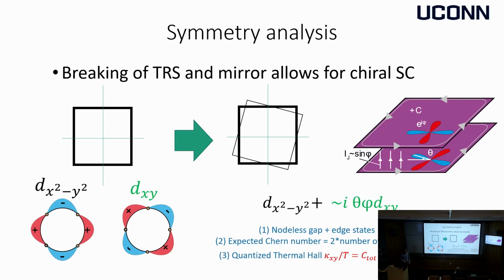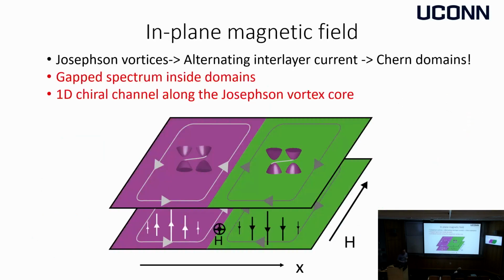So what happens when the current goes down? The edge state becomes broad. Yes, and then the bulk really also closes. Oh, I see. So what really happens is not even the issue of the gap. You will still have a finite gap, but the edge state becomes so broad that you no longer have edge protection. Yep. Okay, even before you close the gap as well.